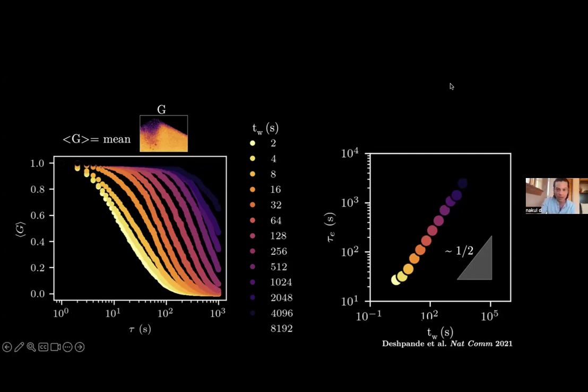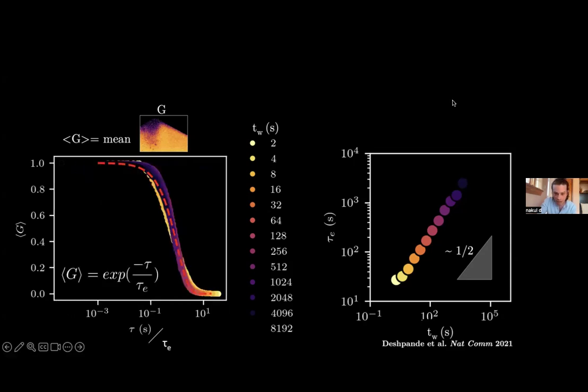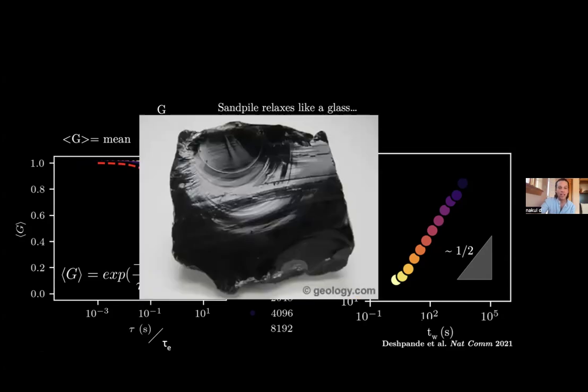And this becomes important because we extract this time and are able to use this time to collapse all of the data onto a single curve, which is a stretched exponential function, essentially. And the reason why that is important, because the stretched exponential function is one that is generically used to describe the relaxation of glasses and glassy materials, okay? And so what I'm telling you is that the sand pile, as you pour it, relaxes like a glass. And we're familiar with glasses in a geological context. If you take a magma or lava and you supercool it, you produce obsidian, right?